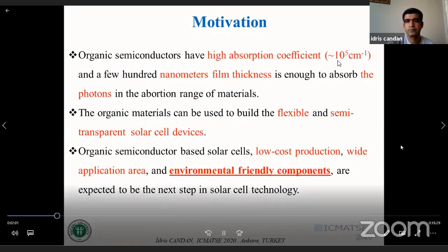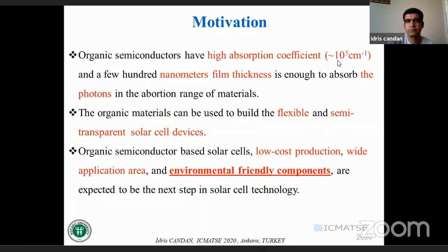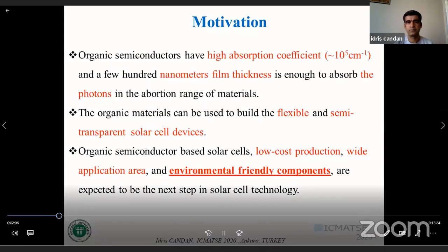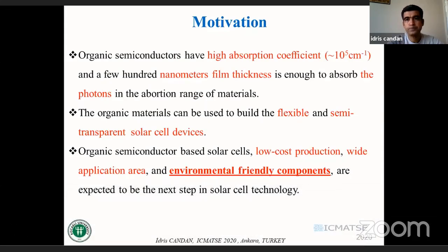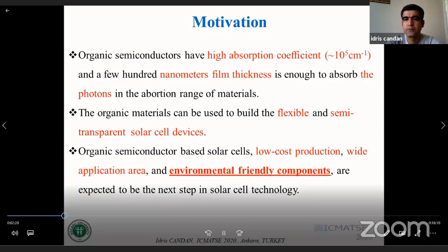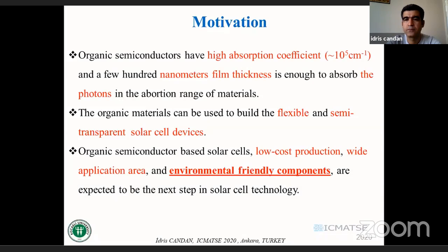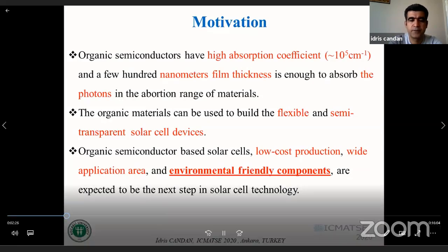Organic semiconductors also have a high absorption coefficient, approximately around 10^5 per centimeter, and a few hundred nanometers of thin film is enough to absorb the photons in the absorption range of the materials. Organic materials can be used to build flexible and semi-transparent solar cell devices. Organic semiconductor-based solar cells, with low-cost production, wide application area, and environmentally friendly components, are expected to be the next step in solar technology.